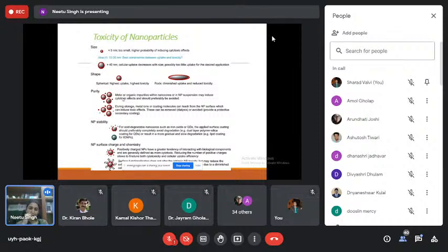The surface charge on the nanoparticle is also important. For example, if it's a highly positively charged particle, the surface of the cells is negatively charged, so it can interact with the negative charge through electrostatic interaction, and because of that, it will just rupture the cell membrane. Okay, and that will be very toxic. So as I said, there could be many reasons for toxicity. These are about the nanoparticle, basically the physicochemical properties of the nanoparticle, right?